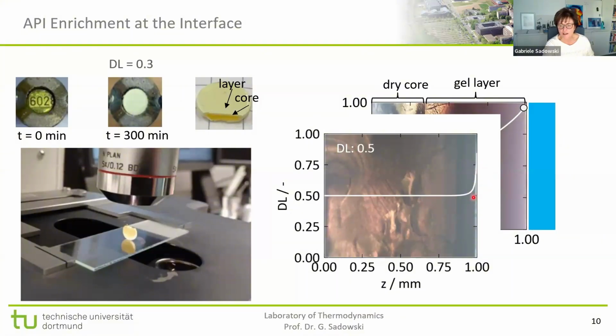This is the same thing, but for higher drug loads, where you can see this was 0.5. This is the one which we still have in the dry core. And again, water comes from the right to the left. So the dry core is quite dry still after 5 hours. It's more or less unchanged. And we have again a layer formed which more or less contains exclusively the API. And of course, this does not want to get dissolved. And once you have this layer, and this layer doesn't dissolve, of course, nothing of what we have inside will ever dissolve. And this is obviously a problem if you take a tablet and it never dissolves in the body. This is obviously not what pharmacists want to have.